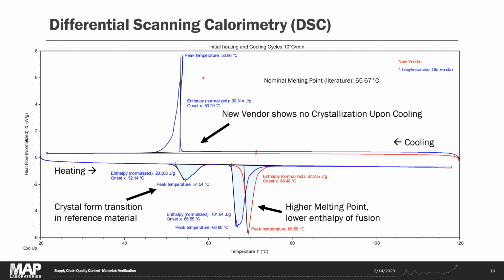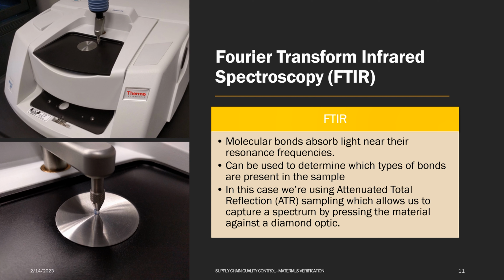These are crystallization events. The main takeaway here is that the melting point of our new material is 70 degrees C, which is a little bit higher than the 67 of our old material. And then on cooling, our new vendor doesn't crystallize at all when we're taking it to room temperature.